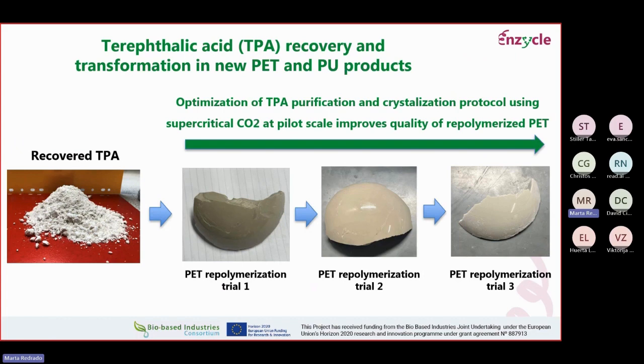In terms of PET repolymerization with recovered TPA, this has been quite a challenging endeavor because you need to have high quality and purity TPA to obtain a good quality PET. One quality characteristic of PET, for instance, is color. As you can see on the screen, we have a gradient from trial 1 to trial 3 in terms of color. The first trial is a bit brownish, and the more we iterate to improve these purification and crystallization protocols, the more we get a PET which has a whiter color, which is a quality indicator, right?